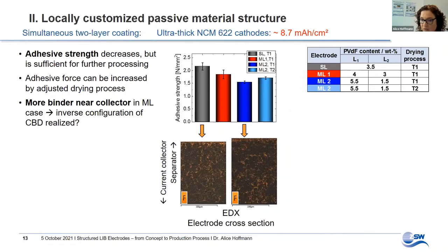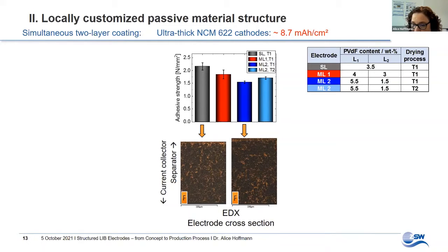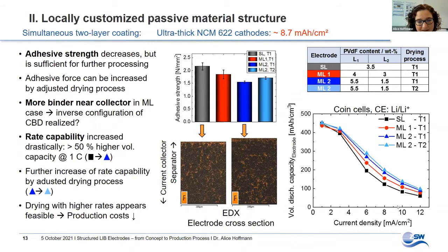In ultra-thick electrodes with simultaneous layer coating, the EDX analysis of cross-sections reveals that more binder remained near the collector than in a comparable electrode prepared with single layer coating. The pictures even suggest an opposite arrangement as it was intended. However, surprisingly, their adhesive strength is lower, although still high enough for a good processability. But adhesion can be improved when the two-layer electrodes are processed with another drying process of the same overall duration, as shown here in light blue.